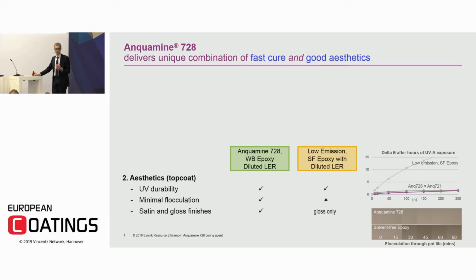Typically in epoxy systems, the amines are very effective in wetting the pigment paste, and then the color drifts over the pot life. So if you start in this room on that corner and you finish in the other corner and you connect the two surfaces, you've got maybe an hour difference, and in that hour the color has drifted. That's what you see displayed over here. The color has drifted in solvent-free epoxy, versus in this water-based system it doesn't, or it does actually to a much lower degree. And you see that you get much better aesthetics in that element as well.